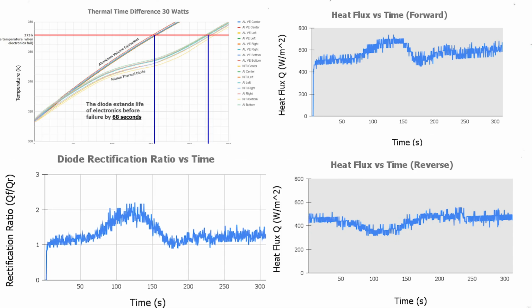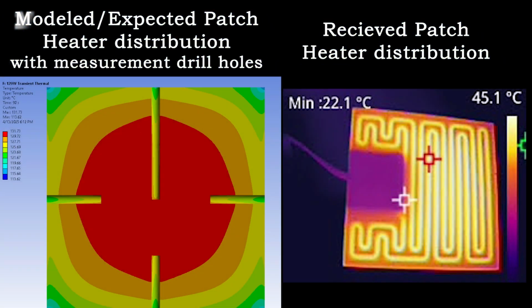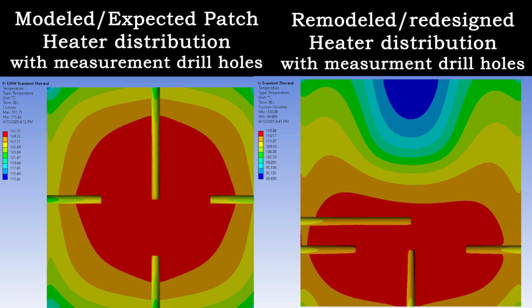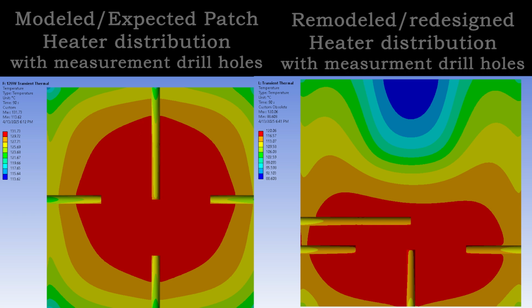rectification ratio. Early on, our data was inconsistent. We discovered there was an issue with uneven heating. Our patch heaters didn't match the assumptions in our models. To fix this, we redesigned the thermocouple placements to ensure one-dimensional heat flow through the sample. That change gave us cleaner, more reliable data.